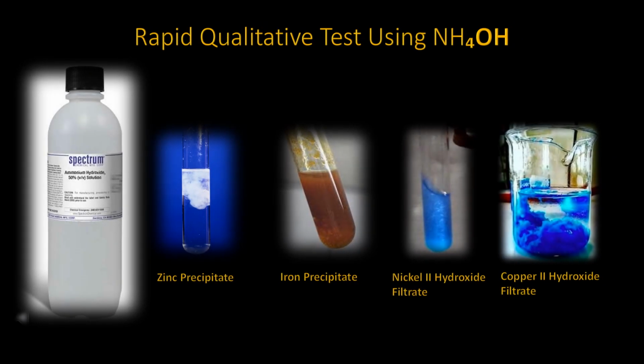The nitric acid solution that was used to test the sulfide minerals, if it produced that brownish colored gas, indicates that the ore had a sulfide complex in it. Do not discard. Let it stand and cool. Once cooled, dilute it with a slight excess of ammonium hydroxide to neutralize the solution. What may happen? A brown-colored precipitate may form. This is an indication of an iron complex. The precipitate will be ferric hydroxide, which is iron(III) hydroxide.